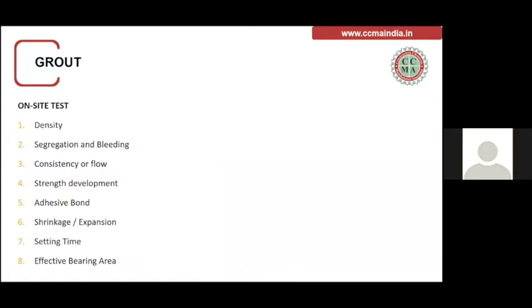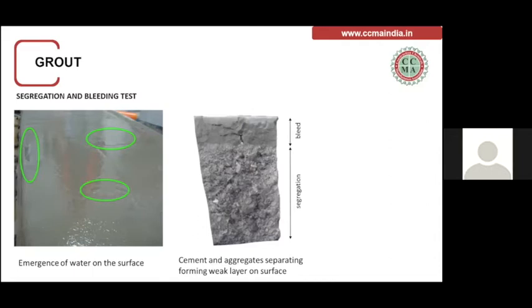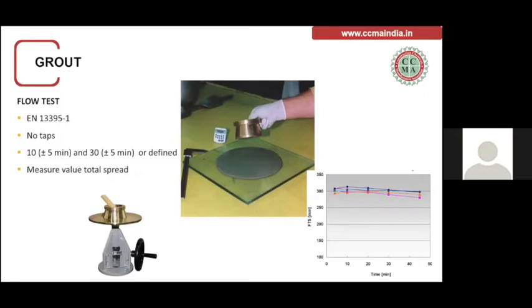Some on-site tests are required, which we should definitely do whenever we do this kind of precast grouting. One is the density, because these are tests which are possible at site. Segregation and bleeding is one of the major challenges. When the grout is being poured or applied, there should not be any bleeding on the surface, because this will lead to segregation and then problems in the end result. This is one of the major challenges we can see during grouting application. Flow is a very important aspect, especially for precast construction, because the flowability decides whether the grout has reached all the pockets or not.